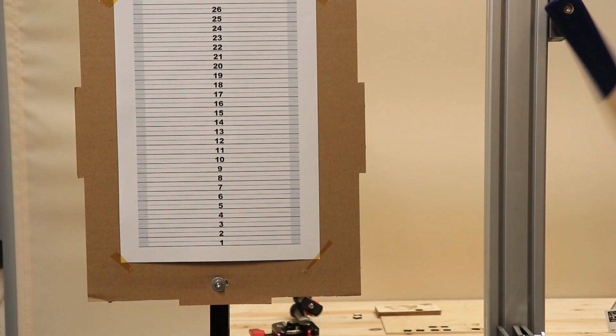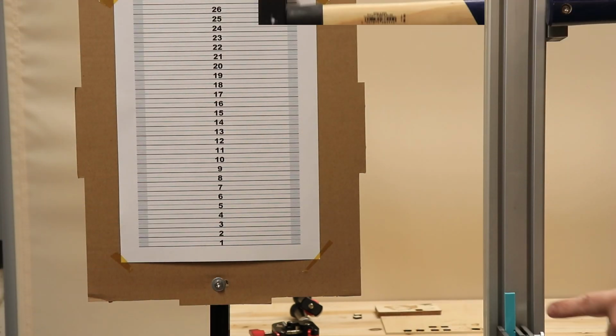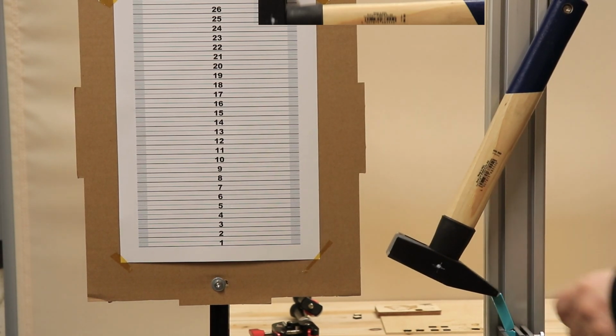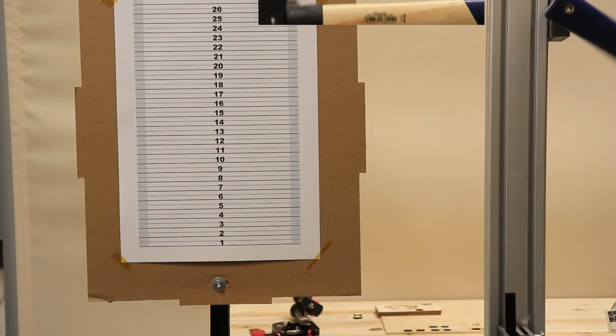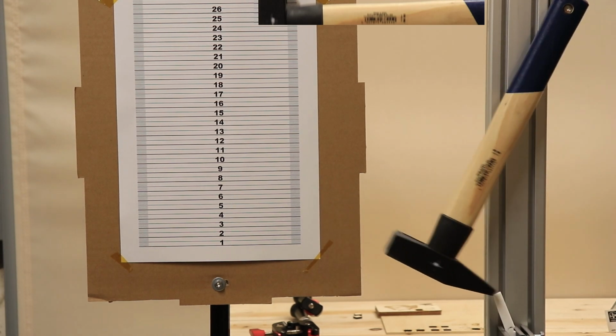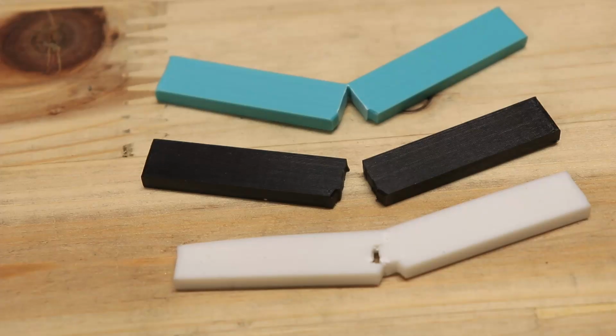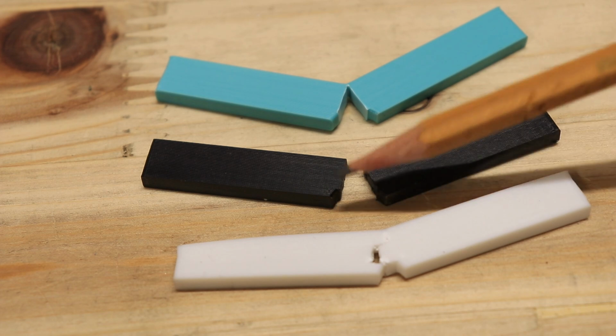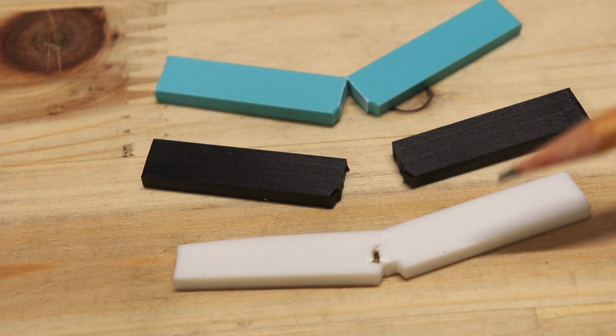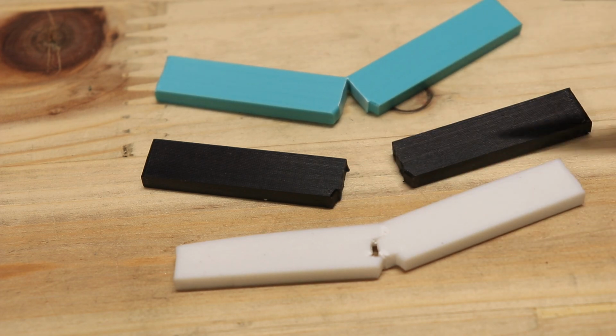Zero position, PolyMax PLA, PolyMax PETG, PolyMax PC. And interesting, after the test only the PETG broke completely, PLA not, but this was very tough, the polycarbonate. And now let's analyze the footage.